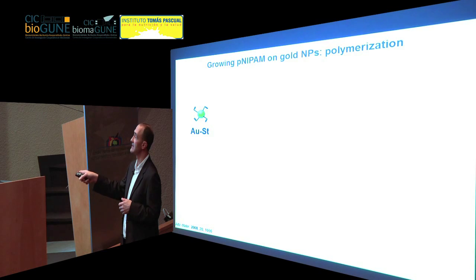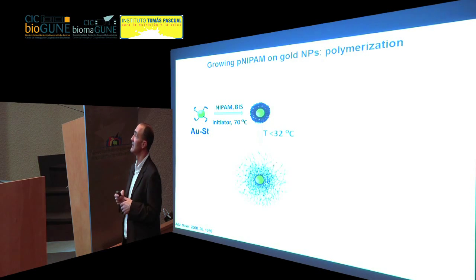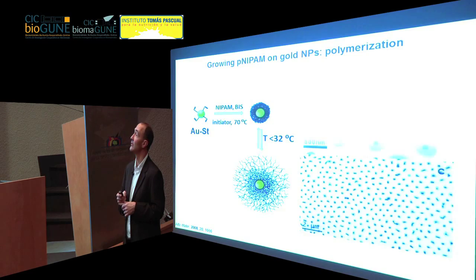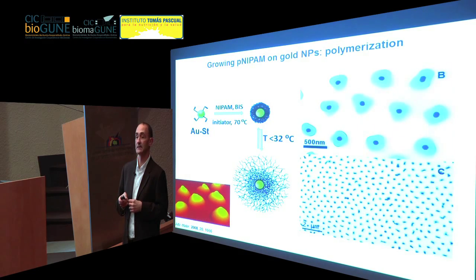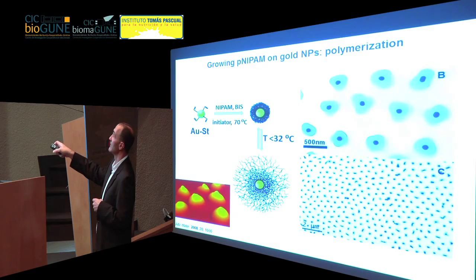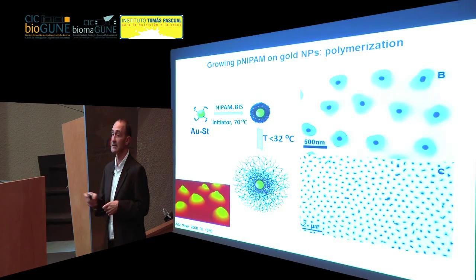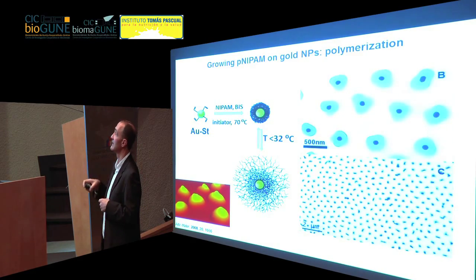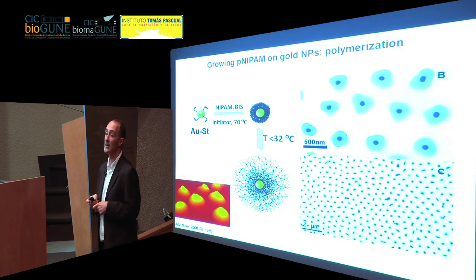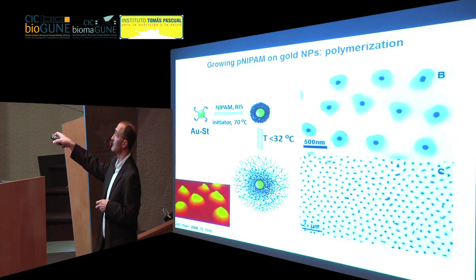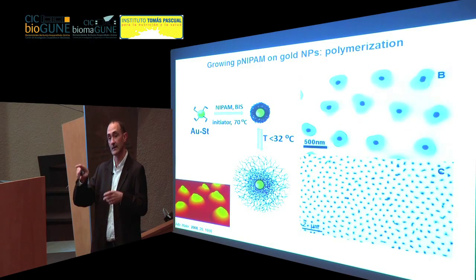So we had to do first some surface modification, and then from there we could grow the shells of this smart polymer on the surface of the gold nanoparticles. We got these nice pictures showing the core shell structure, so the dark dot in the middle are the gold particles, and the lighter halo is the polymer. You see that the shape of the polymer is not perfectly rounded.